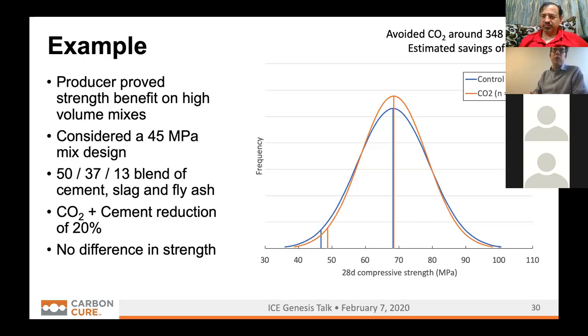This example was an example thereof. It had both slag and fly ash. Across our 120 producers, we've had them use this concrete on all sorts of mix designs. So we've seen just about everything these producers will put in a cement mix, whether it's type F fly ash, type C fly ash, slag, limestone additions, silica fume. They haven't reported any unusual interactions between the CO2 and these systems, neither in the fresh state nor the hardened state. In terms of the interaction with admixtures, again, we're depending on the producers to identify anything that might be unusual. We haven't seen them talk about anything that's concerning them.